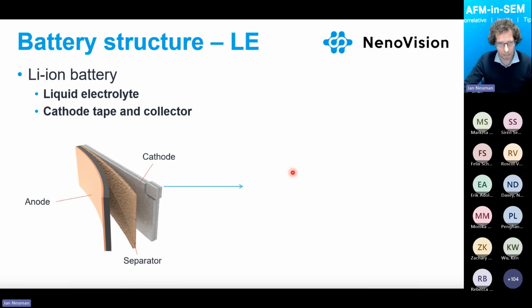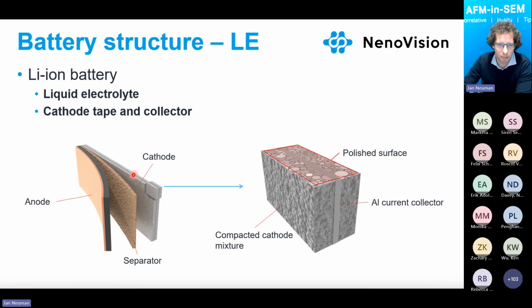Some of the examples will also show lithium-ion batteries with liquid electrolyte. The structure is a bit different. You have a cathode tape, where there is a collector and cathode materials. Then there is a separator and the liquid electrolyte in between. Of course, for SEM analysis, we cannot use a liquid, so you will mainly see the cathode tape, and there is an anode. Again, for the sample, what you will see is mostly the cathode tapes, where we made the cross section in this way. So you can see the cathode particles, and also quite often the aluminum current collector.